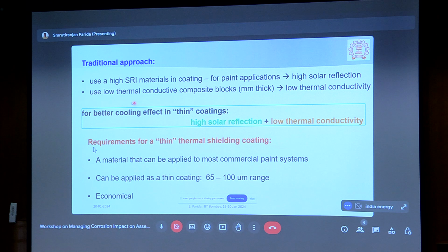The traditional approach is the use of a high SRI, solar reflectance index, material in the coating, used for paint application. Such a coating is based on high solar reflection. But people also use insulating materials, which are very thick, millimeter-thick bulk materials, depending on low thermal conductivity. Our attempt is to combine both these properties in a very thin layer. If you go for a very thin layer, the thermal mass is reduced, and when the thermal mass is reduced, how can we control the thermal conductivity?